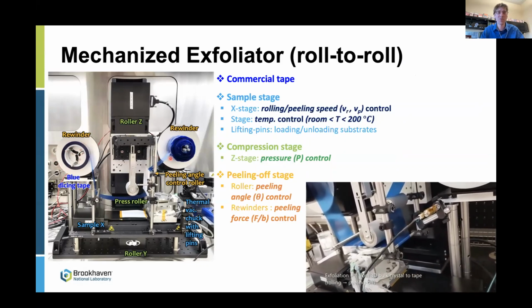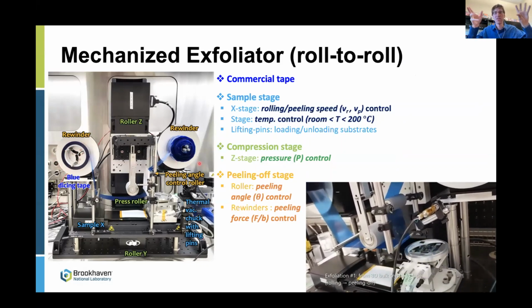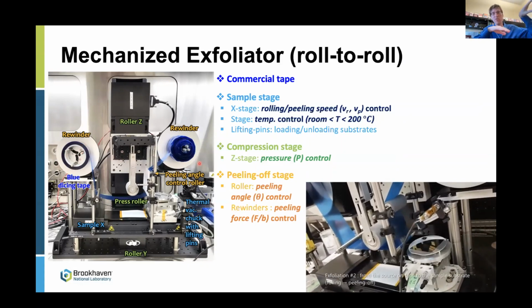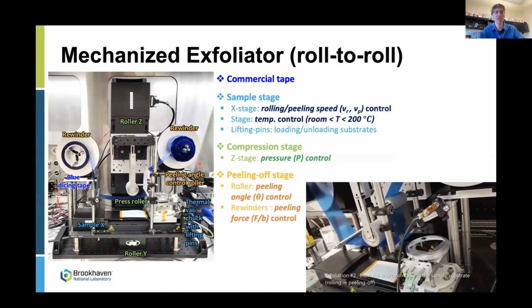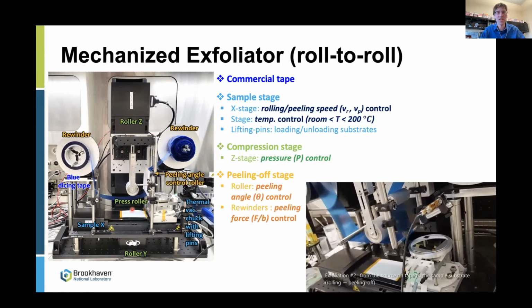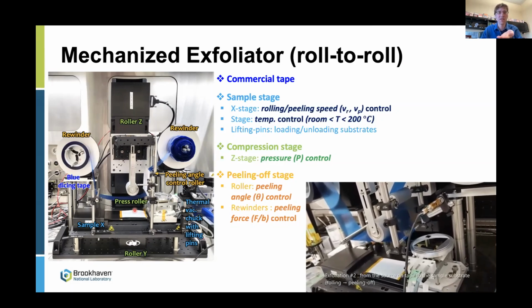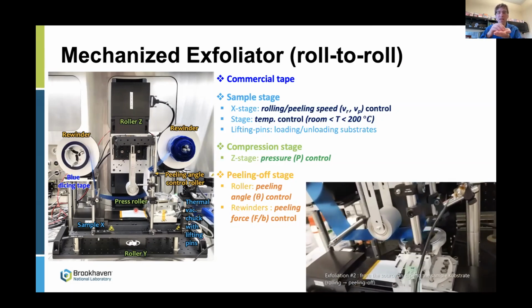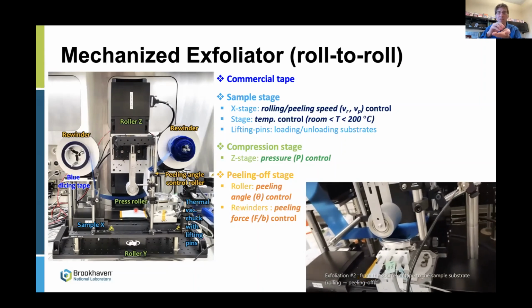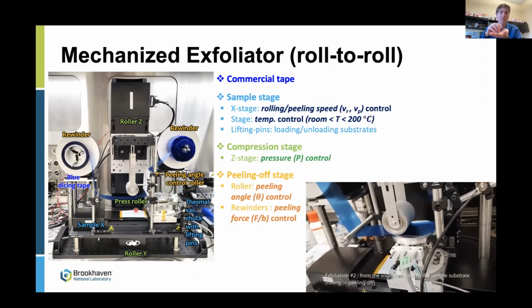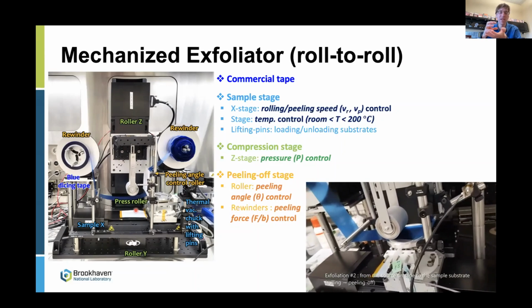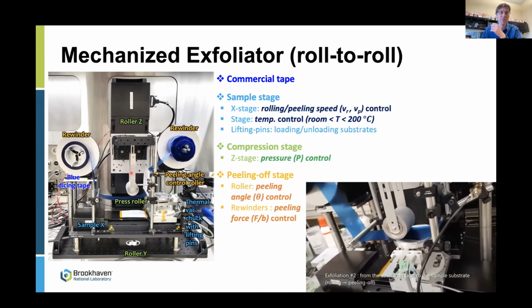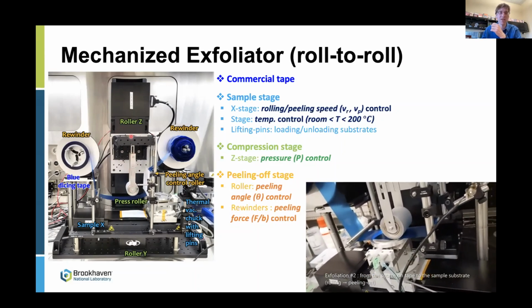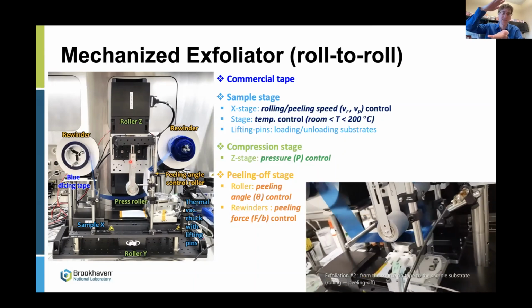And we put this tape on this roll-to-roll system so the system can turn those wheels and move the tape around to bring in some fresh tape. And then what we can do is take a substrate and put it here. We can start with a substrate that has the source material crystal, let's say graphite, if we're trying to make graphene flakes. And then we can use this roller, which is on a motion axis that can press up and down.